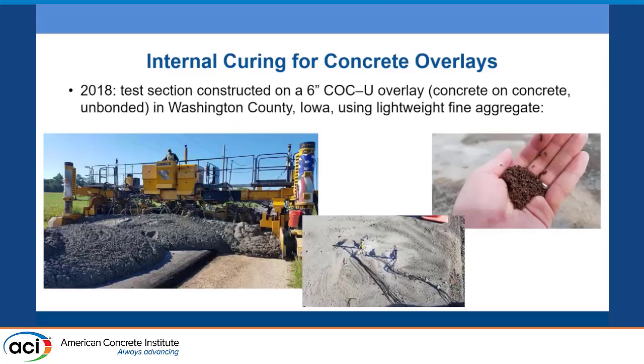So jumping now to the project that was built, this was on a county highway in Washington County, Iowa. This was a 6-inch thick concrete overlay. The terminology you see there, COCU, that's concrete on concrete unbonded overlay. So the existing pavement was a concrete pavement. You can actually see here, though, they're paving on asphalt because they're using an asphalt separation layer to relieve stresses, prevent reflective cracking from the joints in the underlying concrete pavement into the overlay.